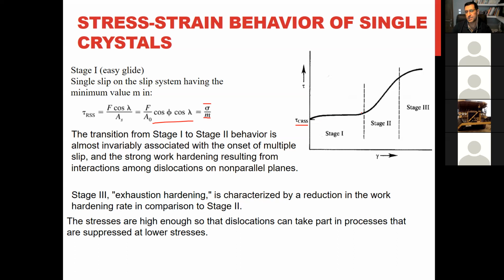But after deformation, and because we activate more slip systems, yeah, so a strain hardening starts, become like this, okay? And this strain hardening increase the stress, that the level of the stress reach to a point that can activate other slip systems that are more difficult to become activated. So again, this slope decrease. Okay, so you understand all these parts by this explanation we did so far. Okay.